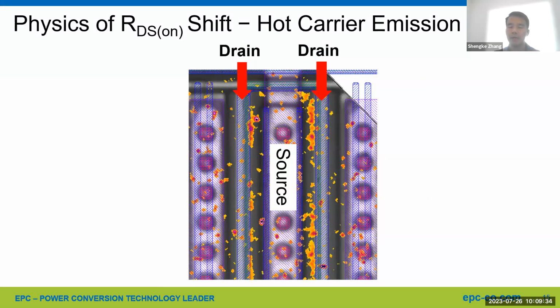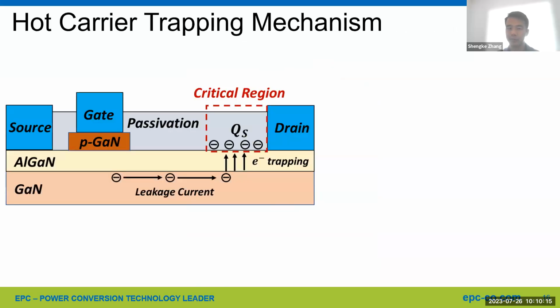If we zoom in on the hotspot image and overlay it with the mask layout, we found that the hotspot predominantly occurred at the edge of the drain contact, as shown in this picture, indicating that that is exactly where the electrons got trapped and therefore responsible for the dynamic RDS(on) shift. By using this imaging tool, we designed our generation 5 and generation 6 devices that are much less susceptible to hot carrier injection induced dynamic RDS(on) shift.